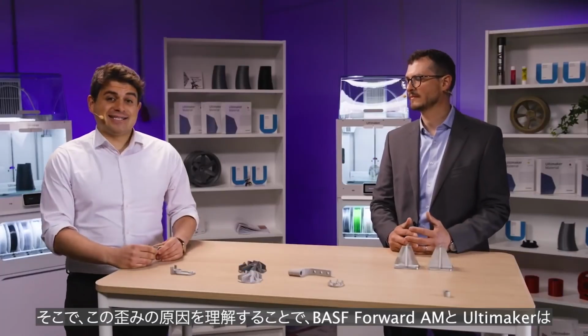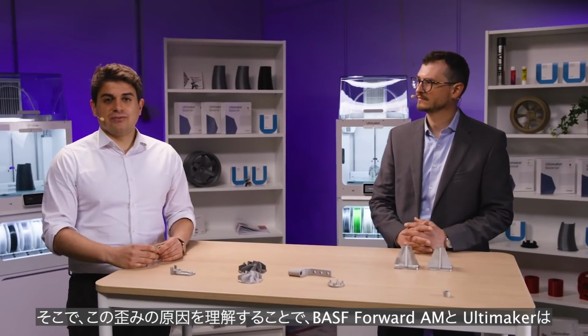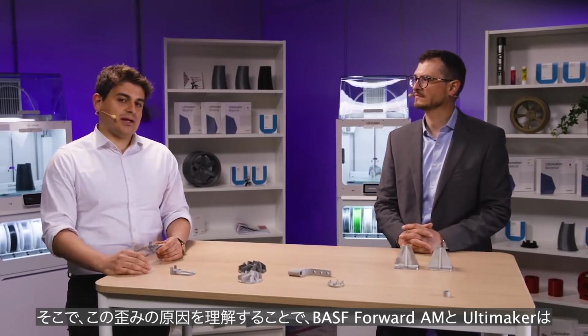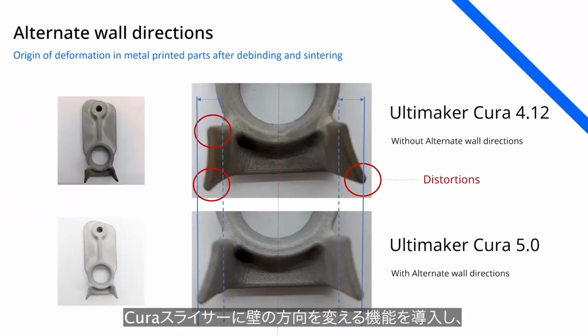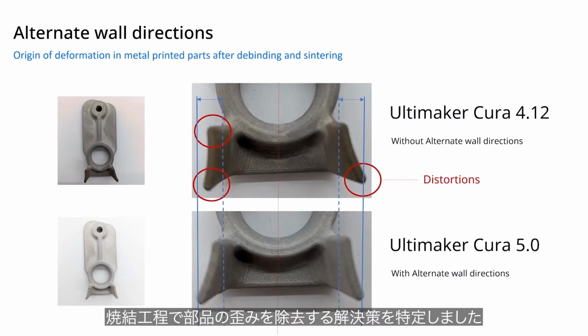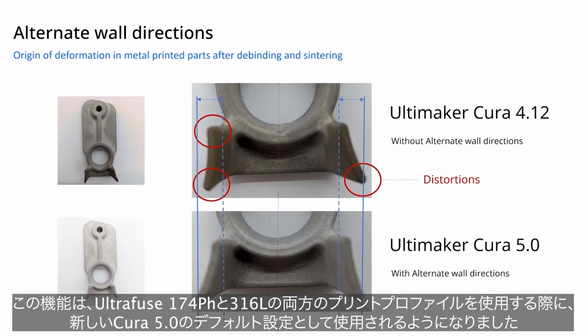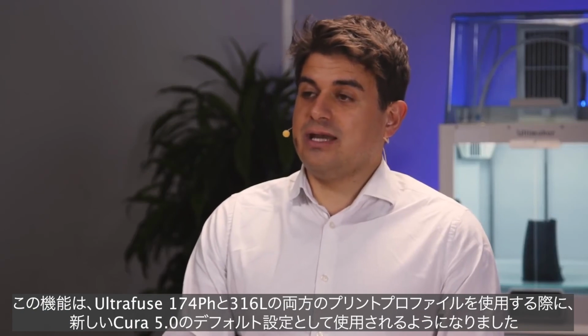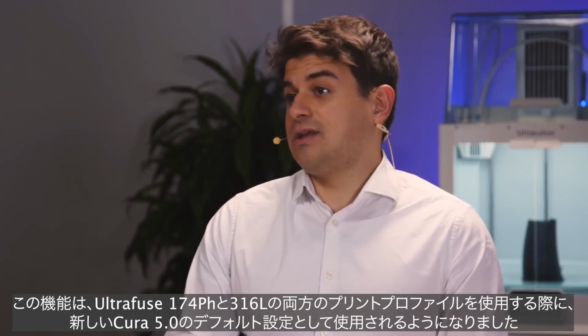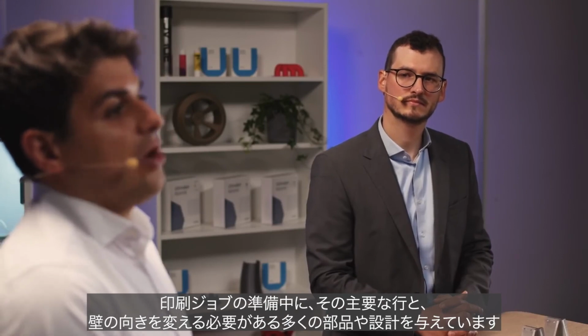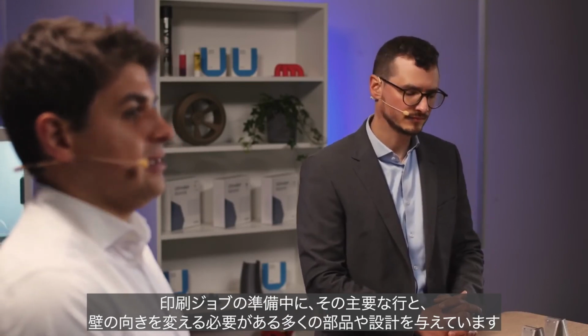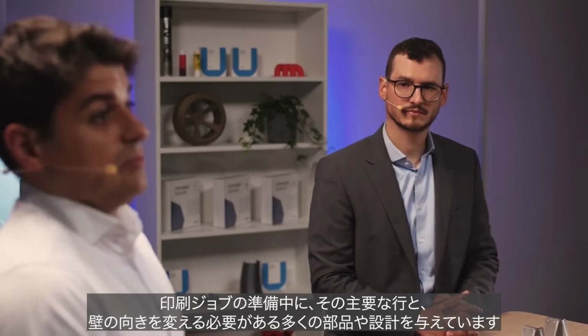So actually, by understanding the origin of this distortion, BASF Forward AM and Ultimaker R&D identified in the introduction of the alternate wall directions feature in the Cura slicer a solution to remove part distortions during the sintering process. This feature is now present and used as default settings in the new Cura 5.0 when using both UltraFuse 17-4PH and 316L print profiles, given its key role and the high number of parts and designs that require the alternated wall direction use during print job preparation.